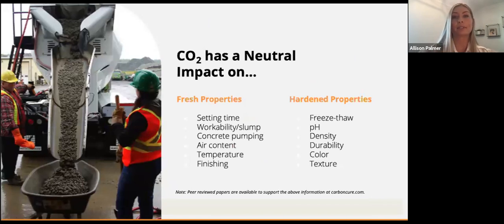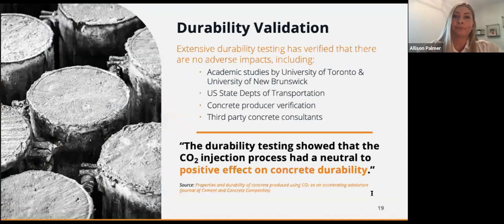It has the same set time, workability, pumpability, temperature, and finishing. No impact on air content and can be used with any admixture, aggregate, cement, or SCM. Hardened properties like freeze thaw, pH, density, durability, and color are also unaffected. And just to reiterate, CO2 has a neutral impact because there's very little of it, and we're just turning it into nano-sized limestone particles. And with that, I'm going to turn it over to Ryan to talk a little bit about durability. Sure. Thanks, Allison.